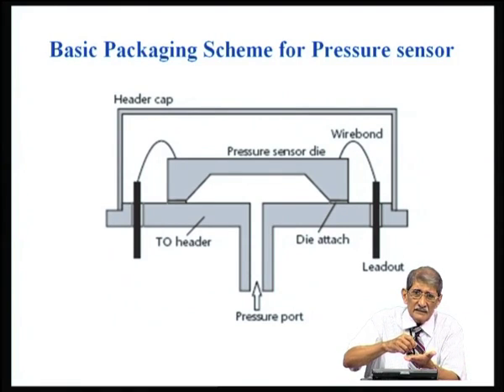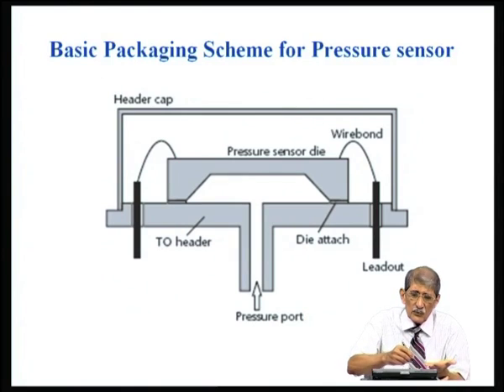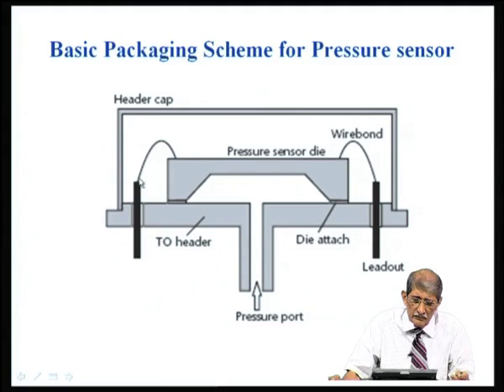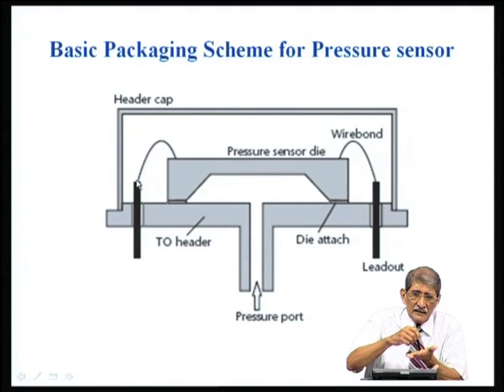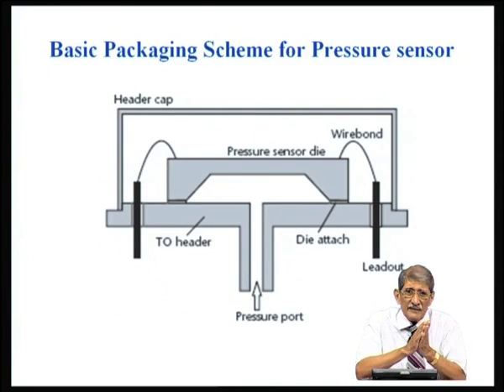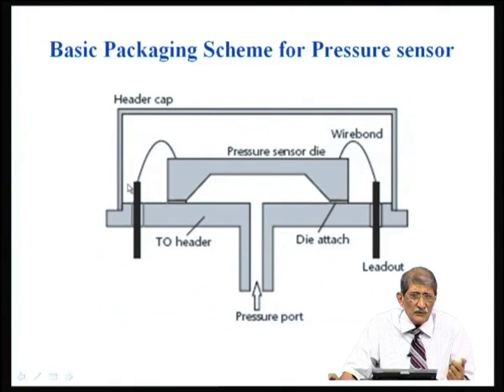When you vibrate it, any little oxide that may be present on the surface will be removed. These wires will be either aluminum or gold wire, okay. And this post will actually be gold coated. So, when you hold it onto that and vibrate it, local temperature will rise and there will be plastic flow, and it will just be bonded onto that. If you take two surfaces and just rub them like that, the local temperature will rise and they will bond. That is the trick that is done here. There is no solder being used.